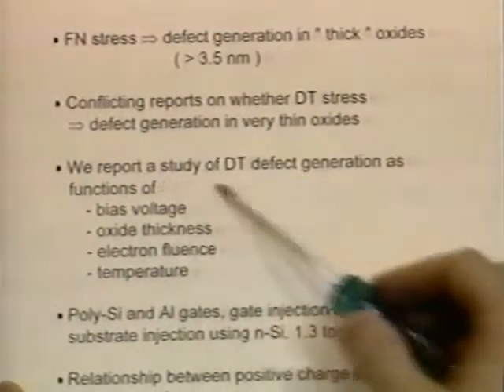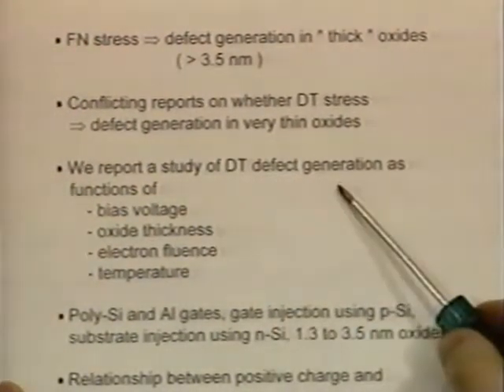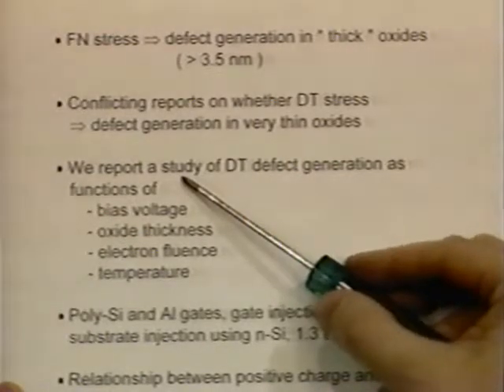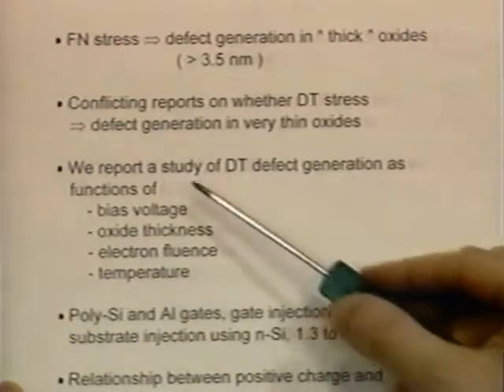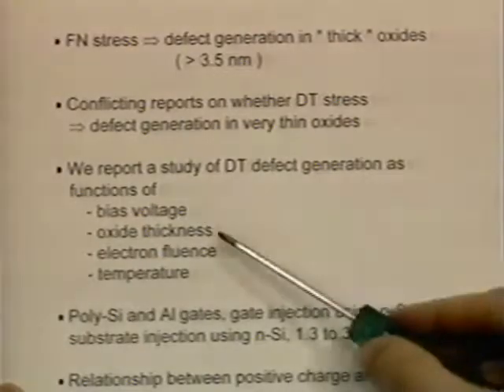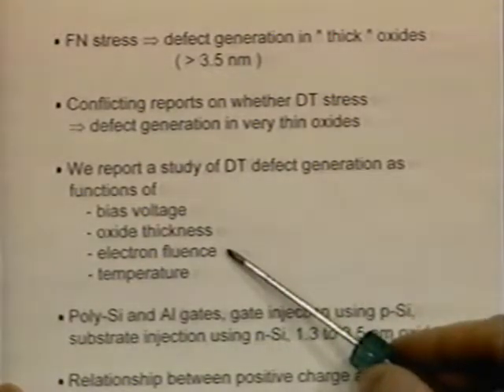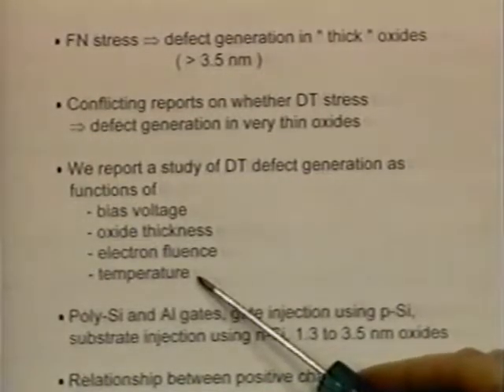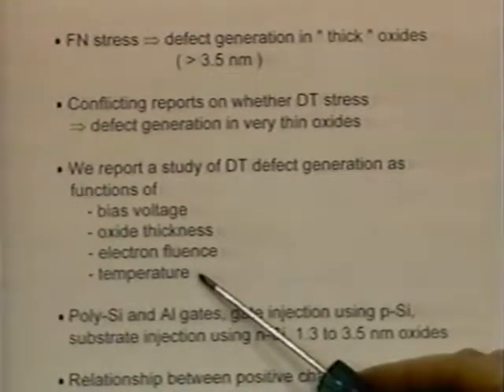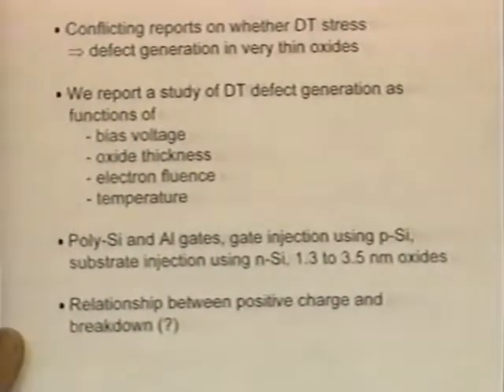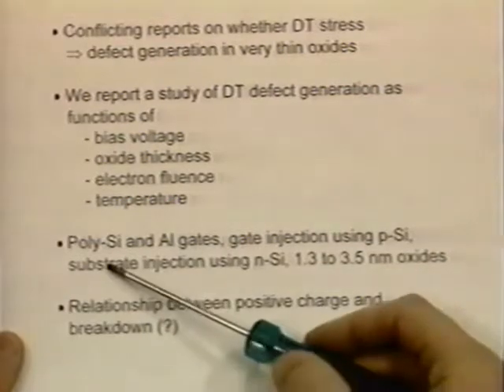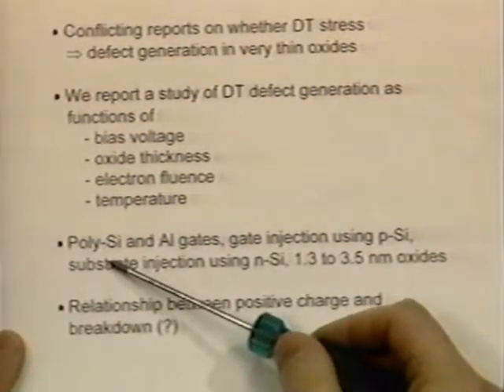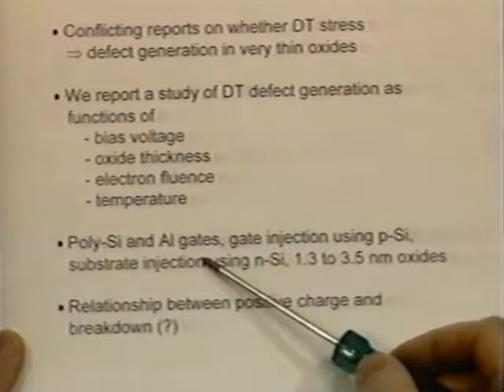So I'm going to report then a study of this direct tunnel defect generation as functions of some of the parameters that you can vary in MOS capacitor structures: bias voltage, oxide thickness, electron fluence, how many electrons pass through the device for this time-dependent degradation. Varying the temperature turns out to be extremely important for understanding the mechanisms. So that people take you seriously, you really have to consider devices that have polycrystalline silicon gates, but it turns out the effect can also be seen in aluminum gate devices as well.